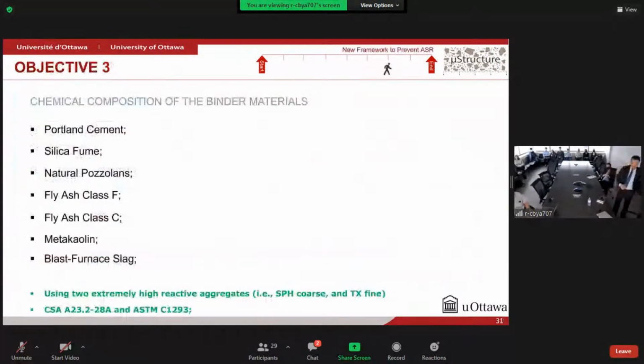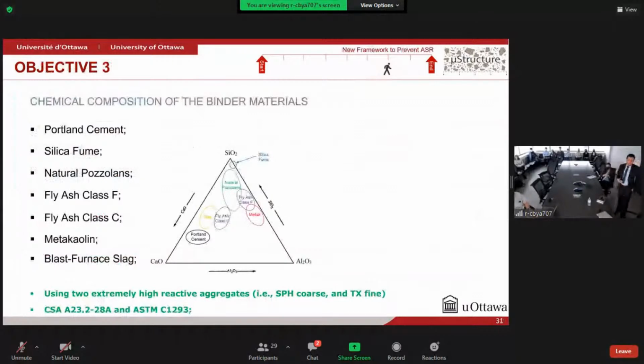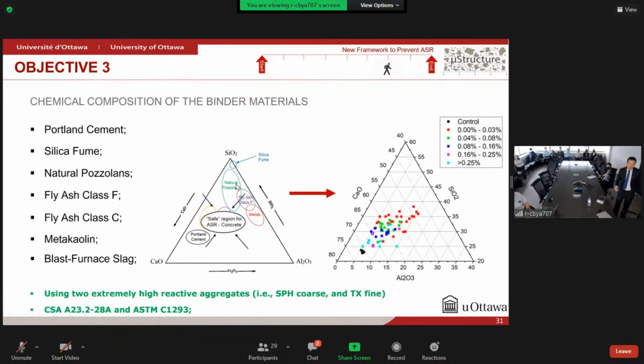And for that, we use our analysis. Now, our analysis is based on the ternary plot of the main oxides found in the binder materials. And I plot here the chart with the most common types of binder materials located here based on their chemical composition. And the idea of putting this together is to show you that what we are looking for is to find different combinations of these materials in which we will have a chemical composition that will locate us in a safe region to prevent ASR in concrete.